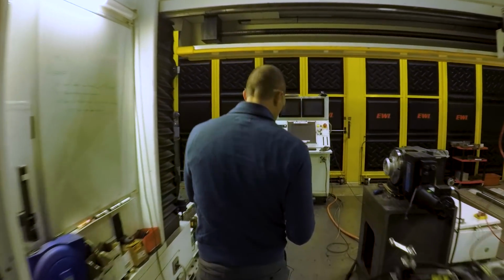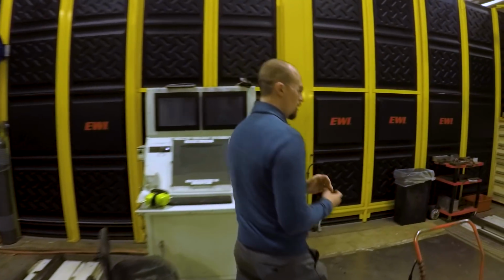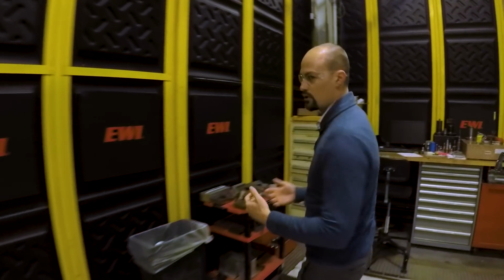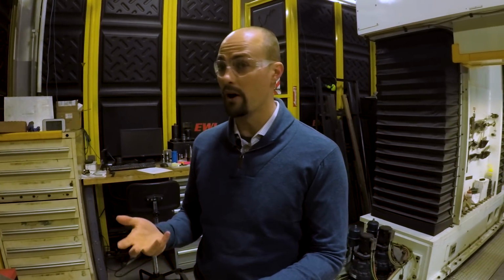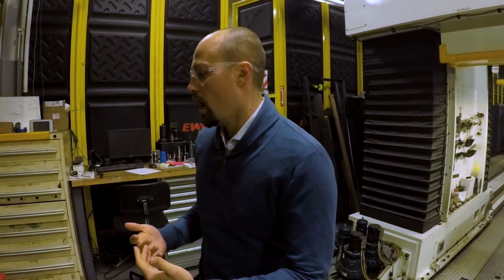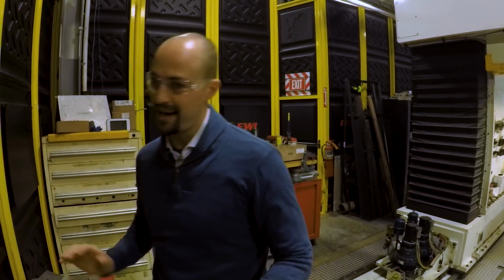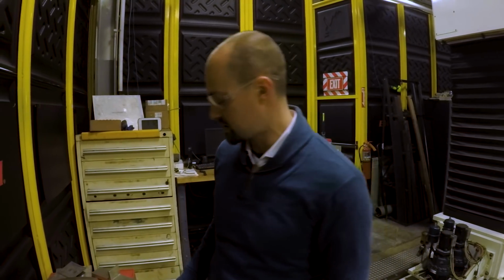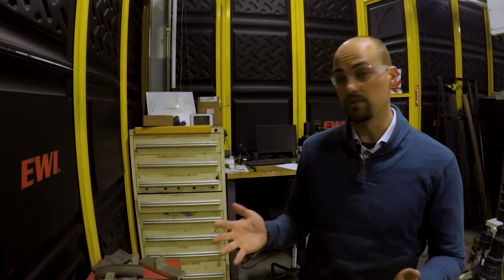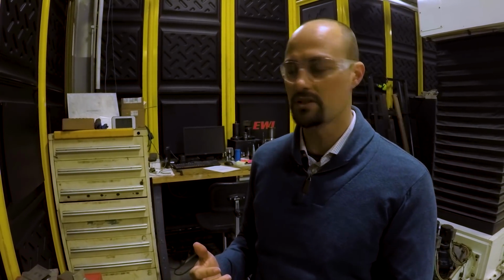The tools are very much a consumable. Yes and no. For thin aluminum, you can run a tool for thousands of feet, and it might only be $50 to $100 once you have them in production. When we get to welding thick section steel, yes, they very much become a consumable and a high cost item. What are they made of? Aluminum tools are just made of tool steel, like H13. As we get to thicker sections, we like to use some cobalt-based superalloys, like a cobalt nickel iron blend material. They still machine like a tool steel, but give us better high temperature properties.